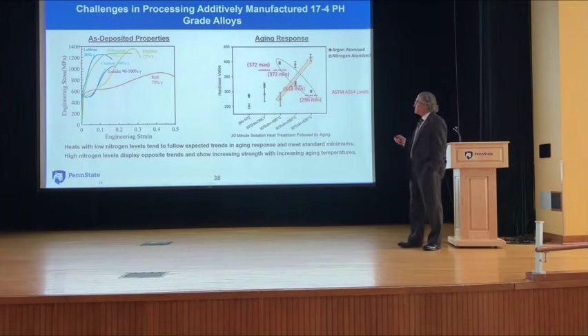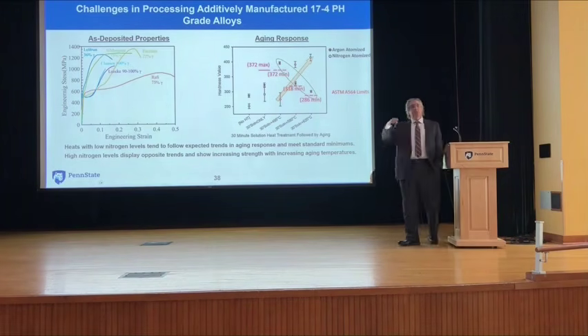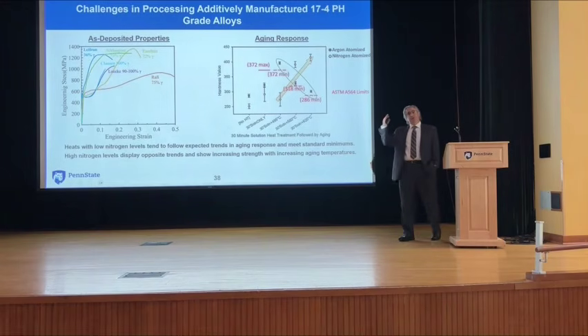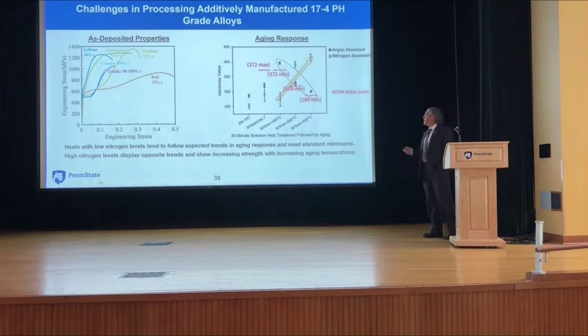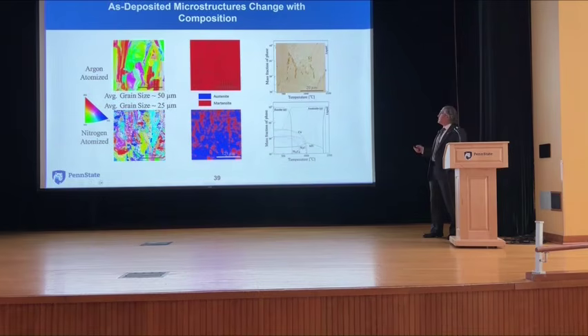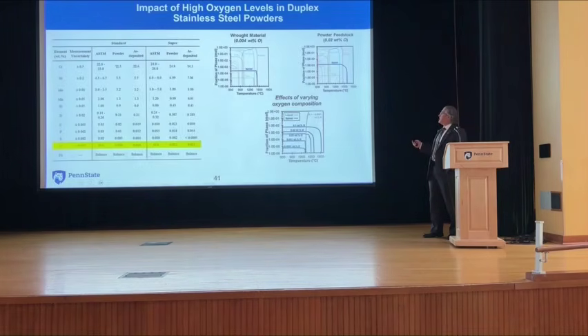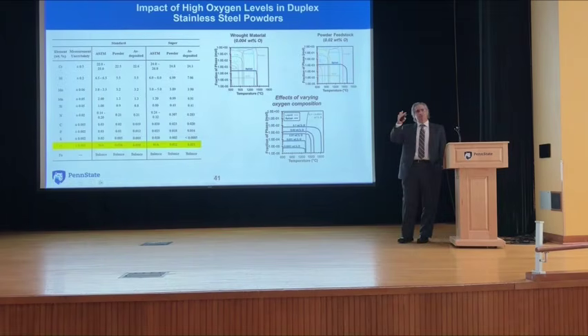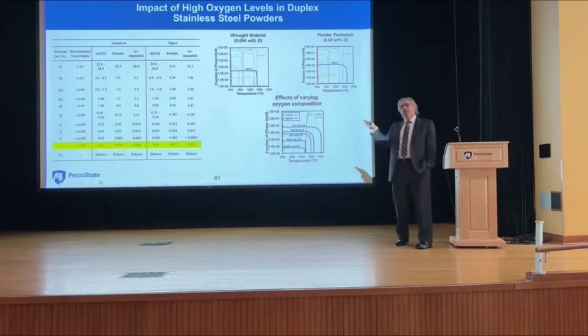Now what we did find was that when you heat treat these, it's supposed to be peak aging at a low temperature and overage after that. We actually found that a whole portion of these got harder at the higher temperatures we aged them at. So some differences there, but I do want to talk about something else. So we have this issue with heat treating. I want to talk about oxide inclusions a little bit.